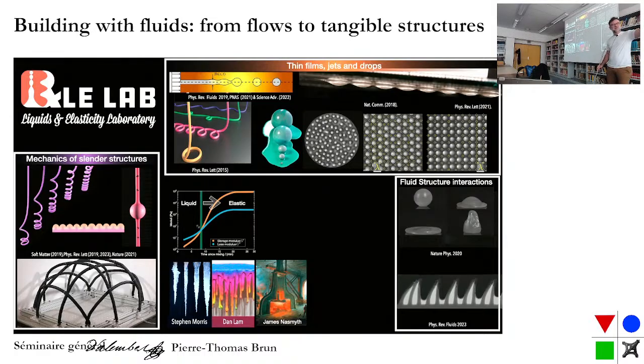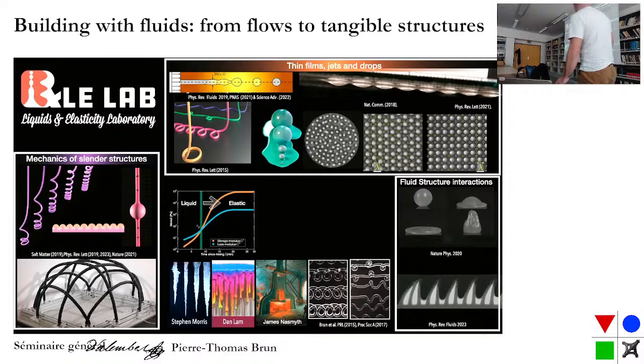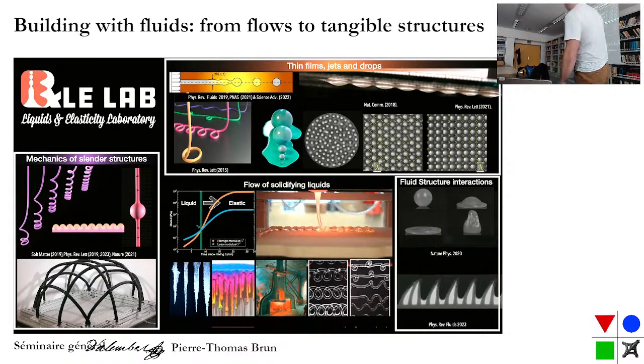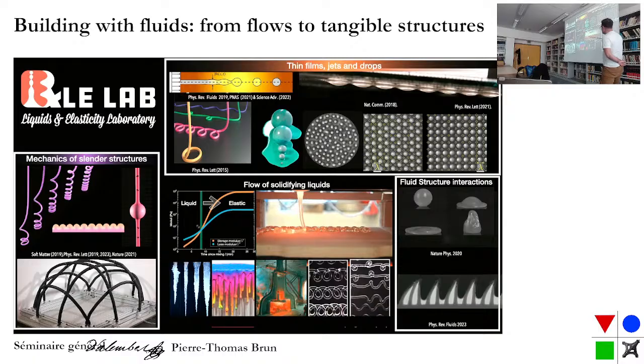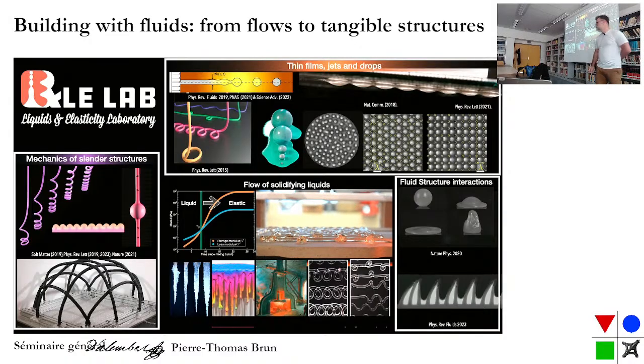So concretes, the glass, and so you use their malleable form, you constrain them in a way that they meet your desired ideal. And so what I propose today is to remove all constraints and to let things flow the way they want. And if you do that, I think my video has disappeared, doesn't matter, but you can have interesting results. So actually, I did my PhD on the coiling of viscous threads, and this is a viscous thread here. The only difference is that this is molten glass. And so when molten glass cools down, you have this nice structure.